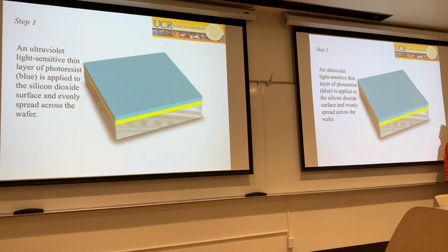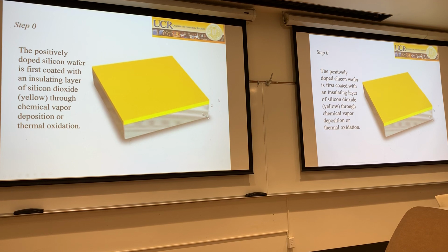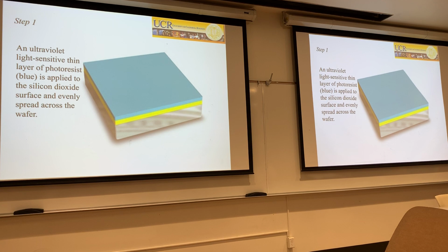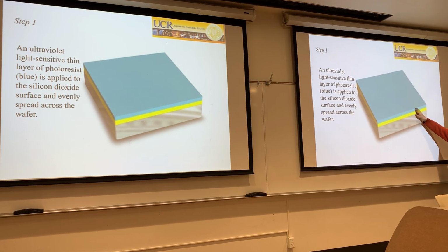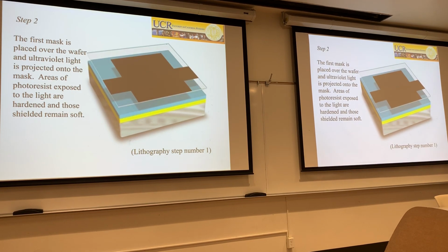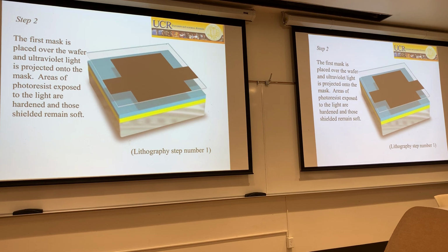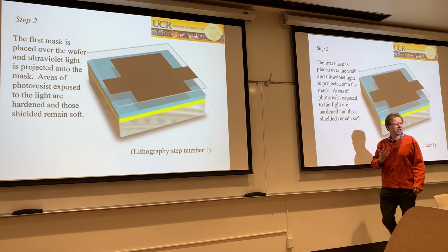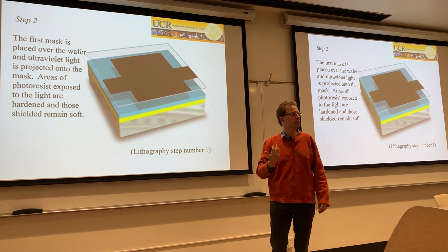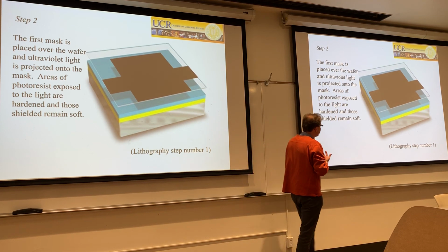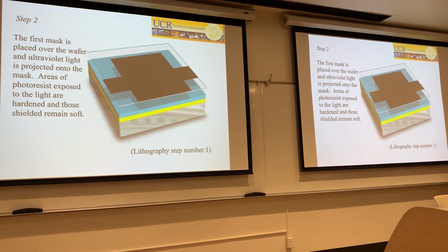So if you think about lithography in the classical way, what semiconductor companies do to make chips is called lithography. It starts out in step 0, you have or you make a layer, and then step 1, you put photoresist onto that. Meaning you spin coat a polymer blend onto this, and the polymer blend is such that when you put a mask or reticle over it and expose it with light, the polymer will change its property. Typically it is so that the polymer becomes soluble where you expose it. In the very old days, you polymerized the polymer and it becomes insoluble through the photopolymerization step. But that has much less resolution than doing it the other way around, having photoactivated acid in the polymer and having it depolymerize that way. So that is really what is being used these days.